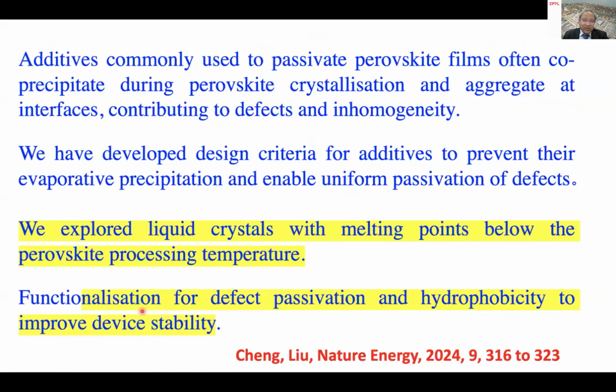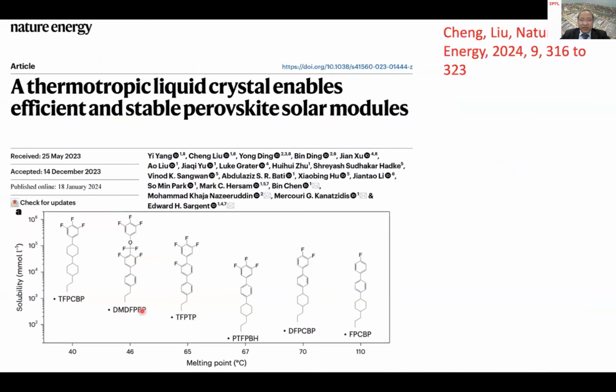we came up with the design criteria. The design criteria is that the liquid crystal has to be hydrophobic. It has to have some kind of fluoride so that when there is an iodide defect, the defects can be passivated. So these are the units, and you can see this work appeared in Nature Energy last year. Here I have shown a couple of examples.